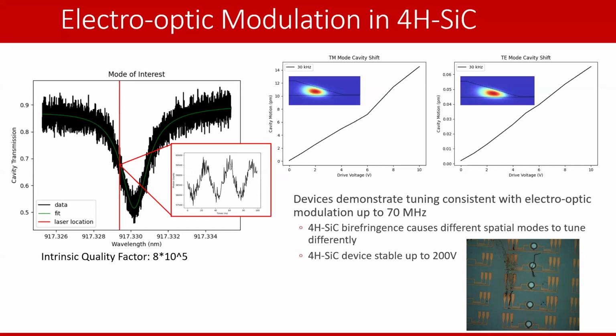And then to further extend this, okay, so this is in whispering gallery modes with a quality factor of 800,000. And these ones are rather large. This was with about 25 micron diameter. So this is a large whispering gallery resonator with relatively good quality factor. We see the linear shift as a result of applied voltage. This is for 30 kilohertz. We see electro-optic tunability up to 70 megahertz, but again, this is not limited by our devices.